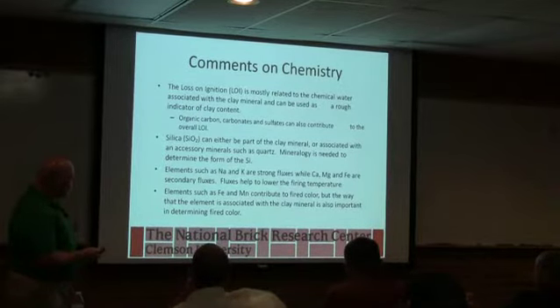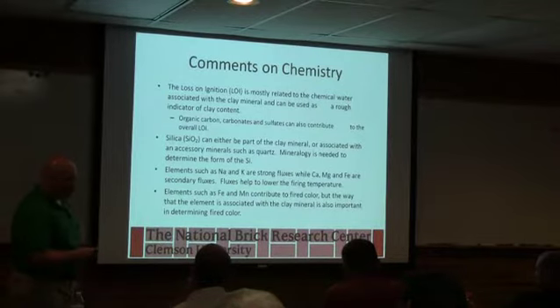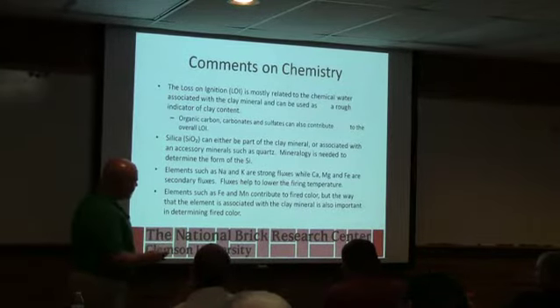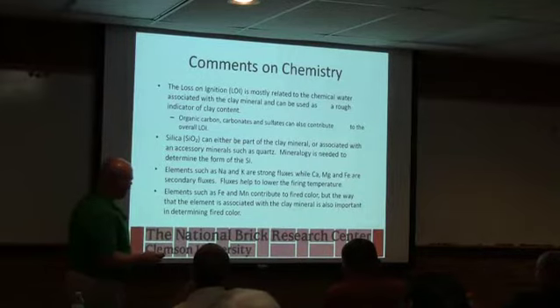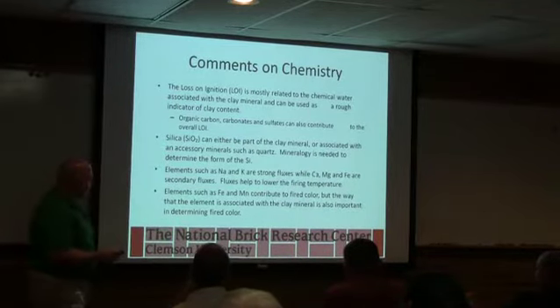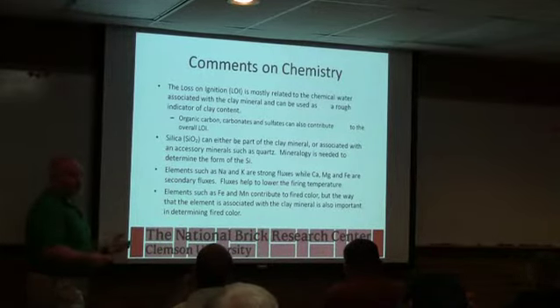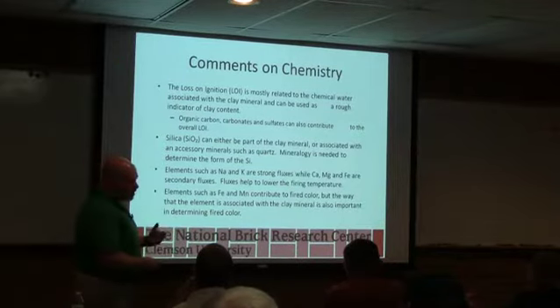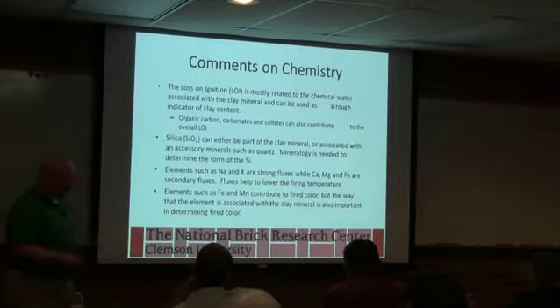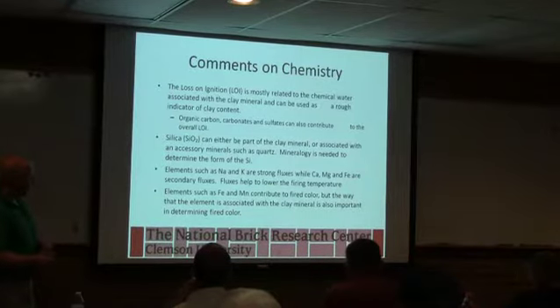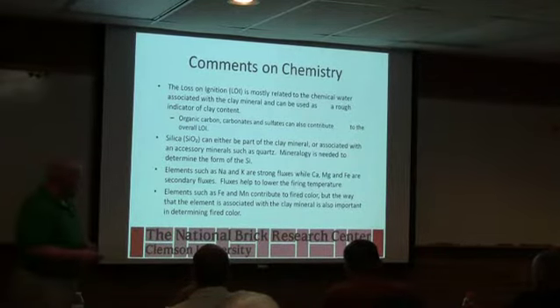We like to look at the sodium and potassium because those are the fluxes and give us an idea of where that material is going to fire out, how much vitrification we can expect. The calcium, magnesium, and iron can also act as a flux, but typically calcium we want to watch out for because if we see a decent calcium content, there's a high probability of lime pops. It's pretty easy to pick those raw materials that are susceptible out. And then iron and manganese give us an idea about fired color.